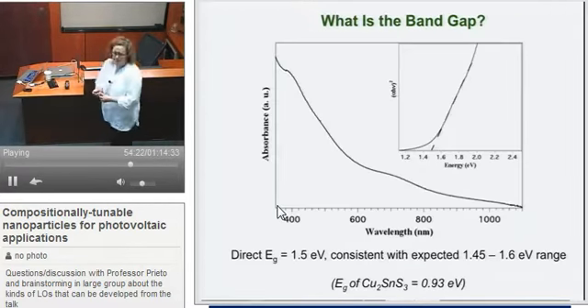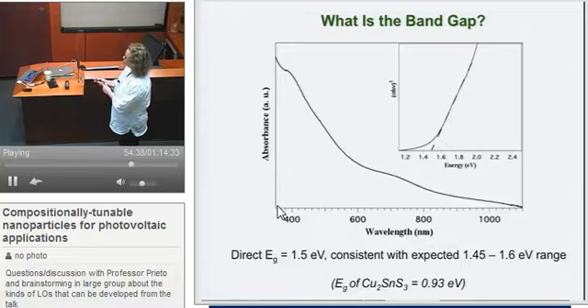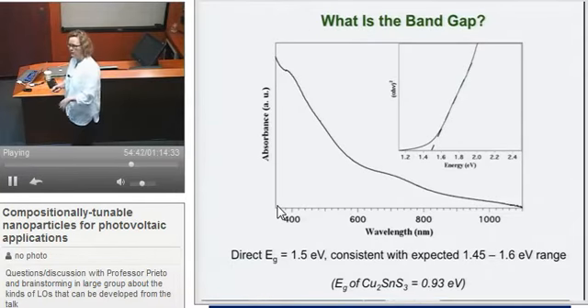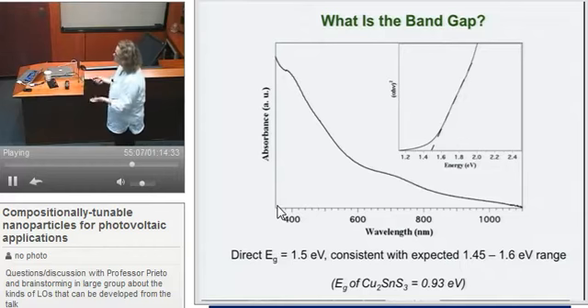We take an absorption spectrum, and what you see here is absorbance as a function of wavelength. You see nice absorption over a range of wavelength, a well-defined absorption event here, and hints of a smaller one at high energy. The way people figure out band gaps in this field is to take the absorption coefficient times h nu squared as a function of energy, look for the linear region, and extrapolate that down, which tells you your band gap. What we have figured out, as we learn more about this kind of spectroscopy, is that if you have mixtures, they don't necessarily show up by this analysis because the absorptions can overlap and you can't really decouple them. But when it's nice and clean, it's reasonable.